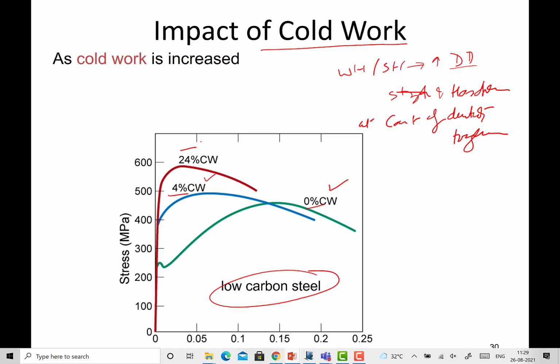If you take any steel weld joint, or any steel or metal, when it is subjected to deformation, certainly it will be experiencing a change in the properties, and this is just indicative of your strength having gone up with, say, 4% of cold working and a reduction in the ductility. Say earlier it was 23%, now it is around 18 or 20, and this is further reduced with the increase of the cold working.